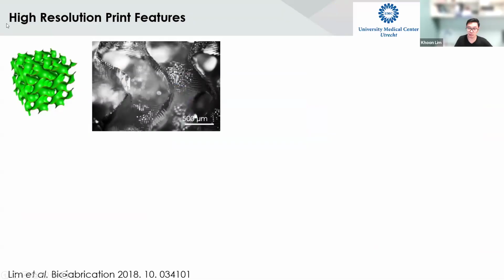If I touch a little bit on lithography, lithography is an interesting technique, mainly because this technique is very much dependent on light, right? So in order to be able to print with lithography, it needs to be a photo cross-linkable material in this case. So we work a bit on trying to get high resolution print features. So everything that I've showed you in terms of the extrusion, the best fiber diameter that we can get between them is about 200 microns, right?